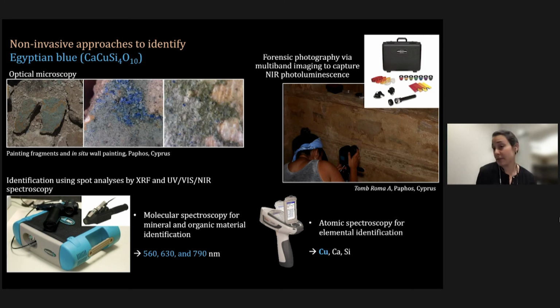First and foremost is forensic photography, so using a modified camera with select excitation and capture with filters. If you use optical microscopy, Egyptian blue tends to be, because it's very coarse, and the larger the crystals, the more blue it is. But then spectroscopy techniques such as diffuse reflectance spectroscopy or elemental spectroscopy, we use these signatures to help us identify Egyptian blue in a painting. But sometimes these are not enough, and sometimes we have very challenging situations where using a modified camera or even just using elemental or diffuse reflectance is limiting.